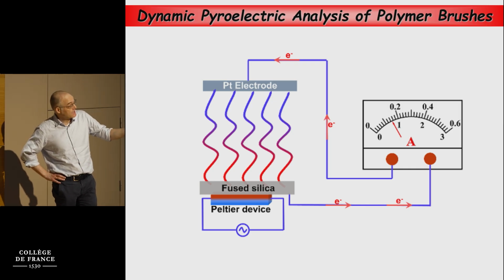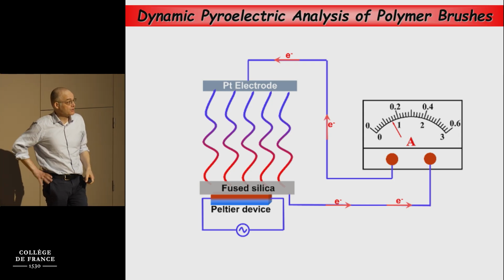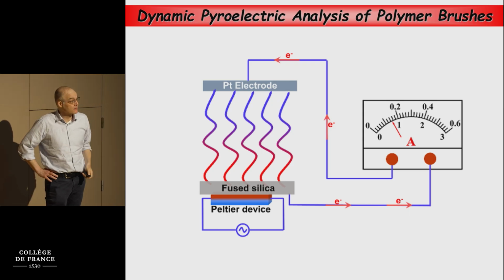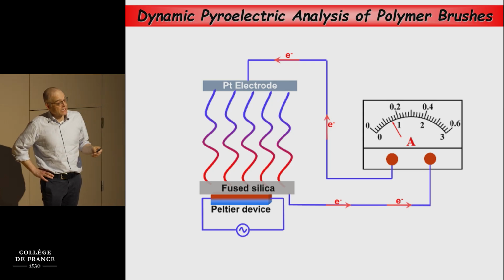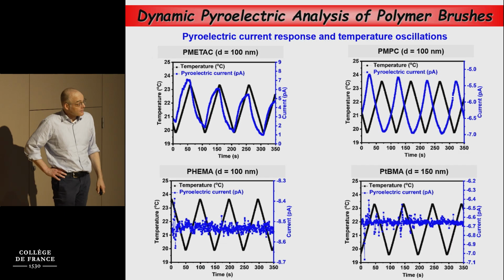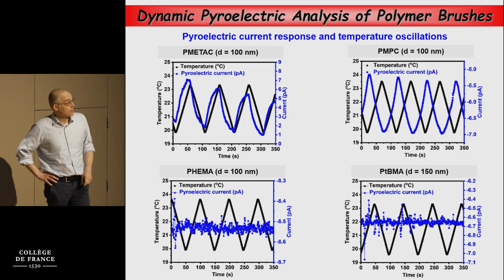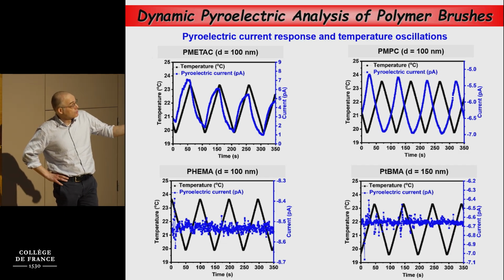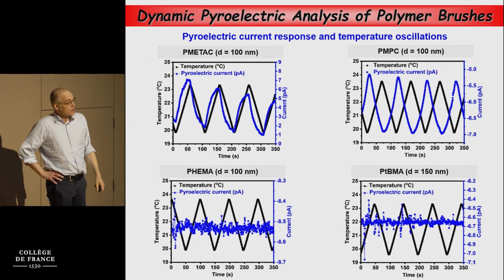These polymer brushes are placed on a Peltier device connected to a circuit, and the idea was simply to expose them to an alternating temperature modulation, 1 and 2 degrees Kelvin up and down, and then try to see whether we can measure a pyroelectric current. What you can see on this slide is a number of examples of the evolution of the temperature modulation, in black. This is about 1 Kelvin up and down. And the corresponding pyroelectric current that we measured in picoampere as a function of time for 4 of these samples.